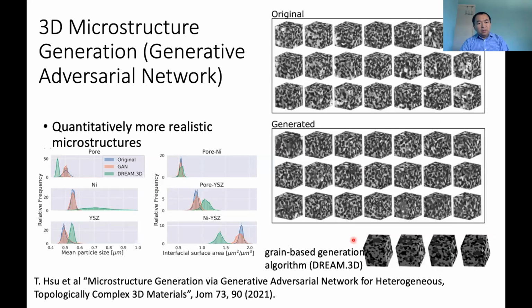And what Hsu and his co-workers did was to develop a 3-dimensional microstructure generation algorithm using the so-called generative adversarial network. And with this, the model was trained from 3-dimensional data. And you can see that visually, the original input image and the generated complex microstructures were very, very similar, and compare favorably with a traditional grain-based generation algorithm called Dream3D.